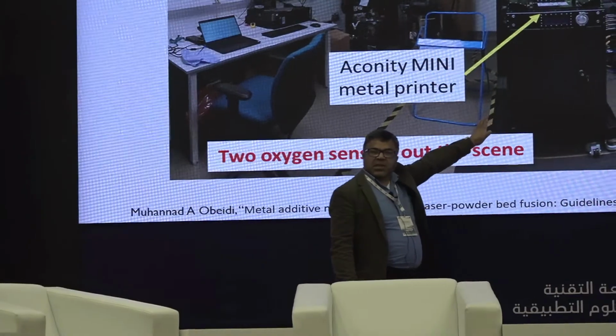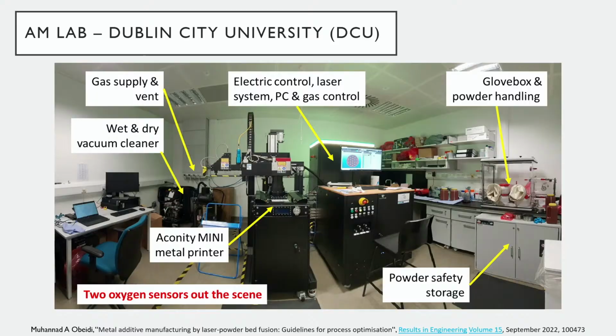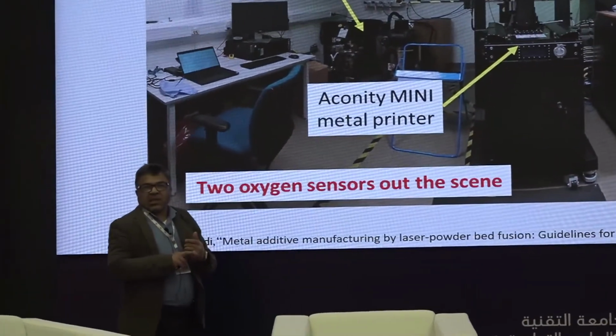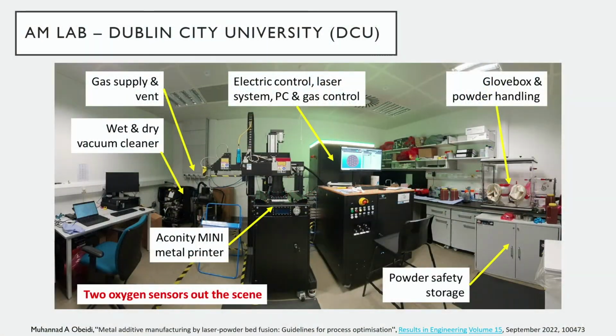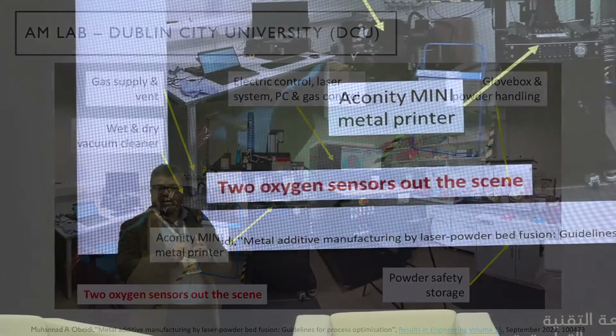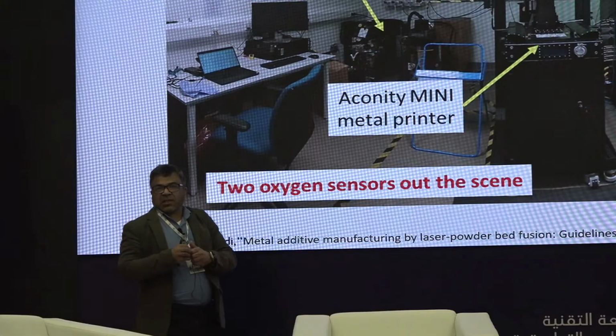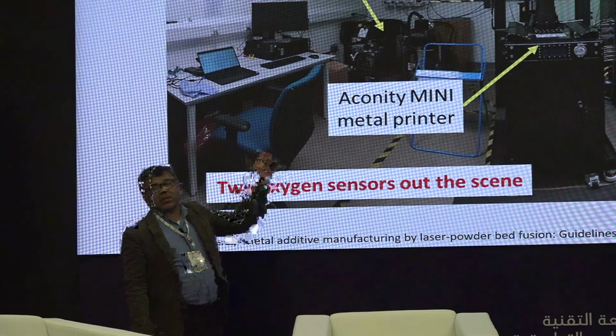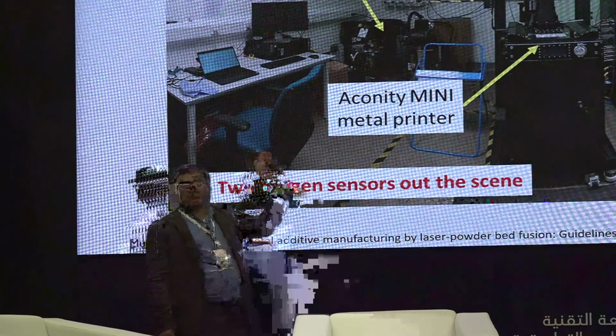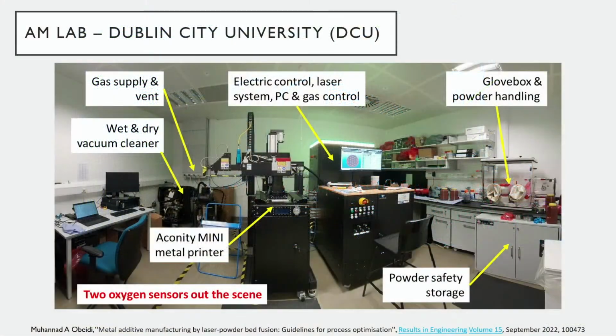The printing process here, because we are using lasers, we have to work in inert gas conditions. Here we use argon. Number one, to avoid oxidation, but very important, these metal powders are inflammable, explosive, and also oxidized. So we have to work in inert gas conditions. We use argon or nitrogen here. When the curing beam is electron beam, the whole process works under high vacuum. Again, these metal powders are explosive and inflammable because of the mass to surface area ratio.